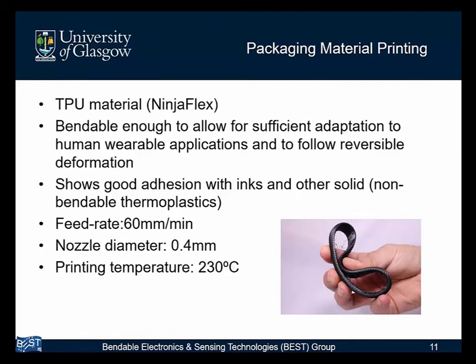So in terms of printing thermoplastics, we're looking at a holistic system of 3D printed circuits. We're looking at some bendable parts and some non-bendable parts. So with regards to PLA and ABS, NinjaFlex binds well, as well as binding with inks. Another important thing to note is that with such rubbery or bendable materials, it's important to print at a much lower speed to avoid any warping of the material itself during the printing process.